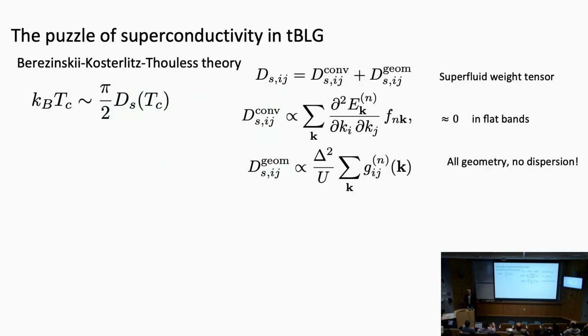Okay? Now, flat bands are great for the reasons I described, but they're very problematic from a very different perspective. Let me try to address this now. This is a slightly oversimplified picture, but the presence of flat bands produces a puzzle for superconductivity in twisted bilayer graphene. Very roughly speaking, in a hand-waving sort of argument, the critical temperature for superconductivity scales like the value of this tensor, called the superfluid weight tensor, which is written more explicitly here. In order to create the superconducting state, which is the superfluid in a certain sense, this is the relationship between the critical temperature and this tensor.